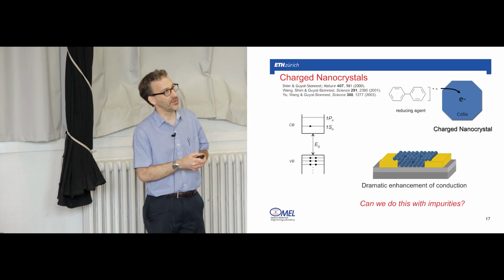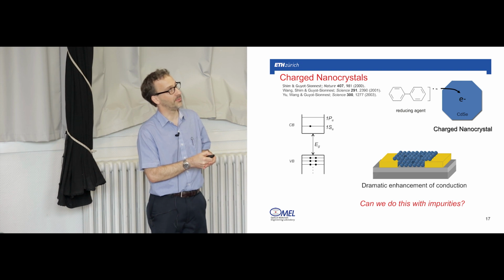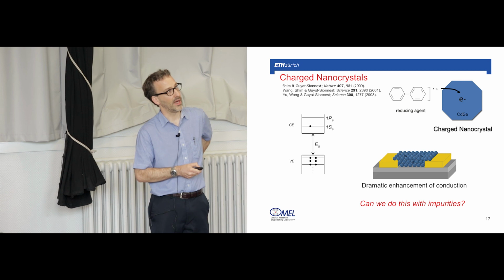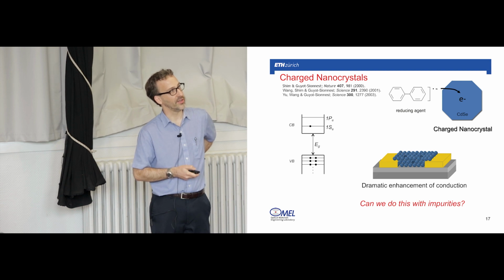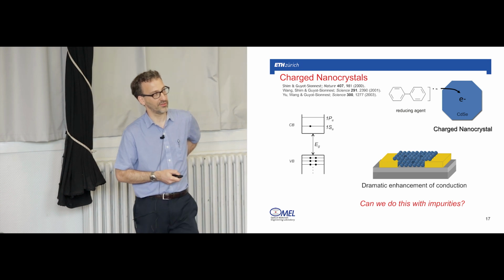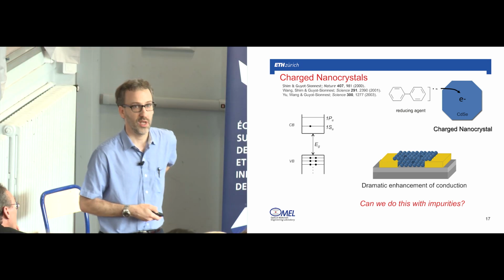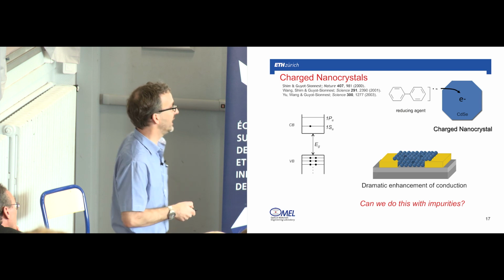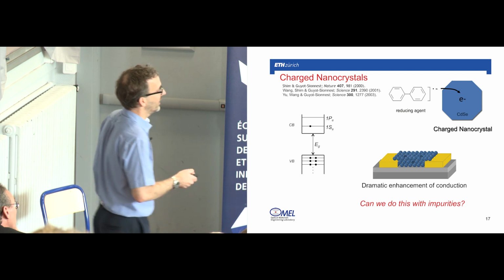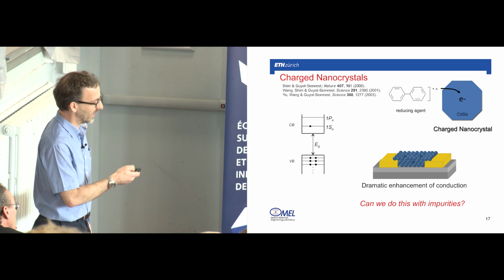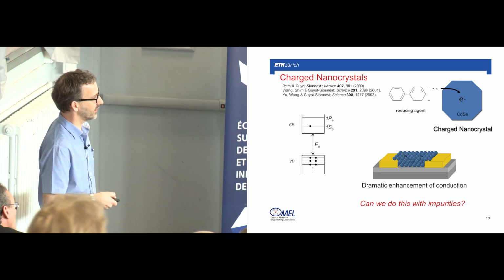So we have lots of reasons why we might think that it's worth trying to get there. Philippe just talked about the experiments that he did on the charged nanocrystals. By either reducing a nanocrystal and injecting an electron, putting it in the conduction band, or in some later papers, as he just told us, you can electrochemically reduce a film of nanocrystals and put electrons in. You could get orders of magnitude increase in the conductivity. So this is a motivation: why can't we do this with electronically active impurities?